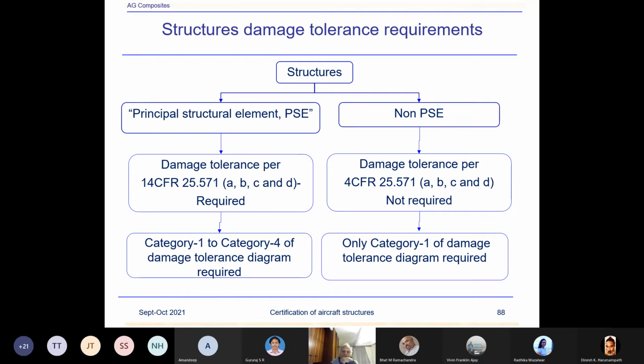So damage tolerance, when you are trying to satisfy the requirements for PSE, which is critical structures, you would consider the damage tolerance per 14 CFR 25.571. That's what we have been talking about, the damage tolerance in categories 1, 2, 3, 4. All categories 1, 2, 3, 4 have to be considered for primary structures. Whereas when you are trying to justify non-PSEs, then this criteria is not applicable. 25.571 not required. Only category 1 damage tolerance diagram required. That is only BVIDs, very small damages, that is undetectable damages, but not the detectable damage for non-primary structures, non-PSEs.